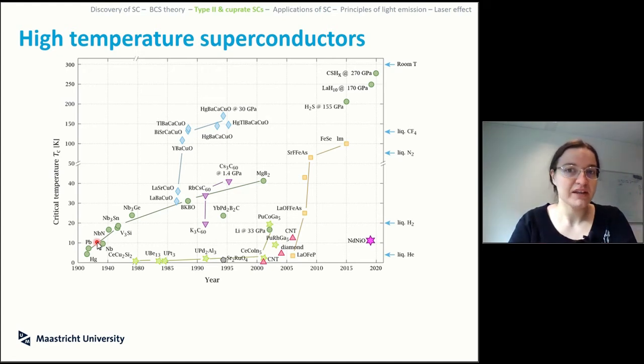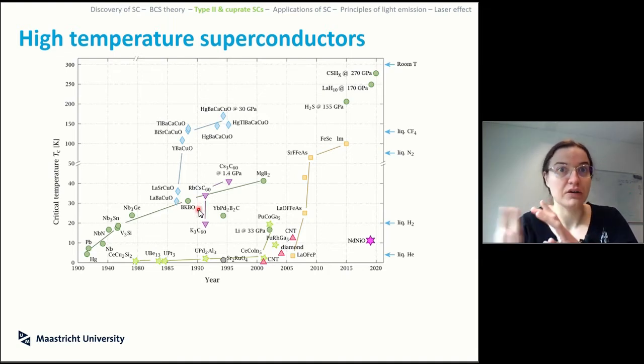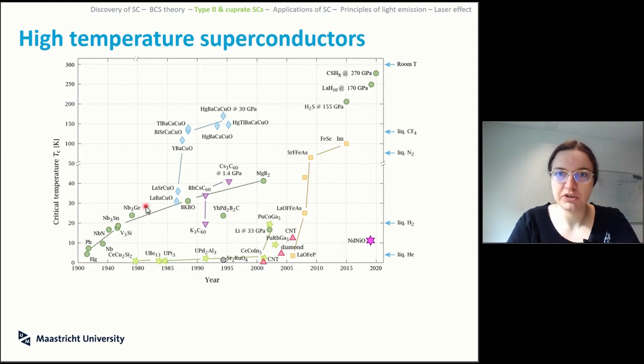And one of the biggest breakthroughs in this field was in 1986, in which they touched onto something that are the high temperature superconductors. And this was the first big leap, discovering this oxide phase, which, unlike the intermetallics, is a bit more like the complex oxides that we've seen in batteries. To begin with, in this composition, it was a lanthanum, strontium, copper oxide type of phase. We showed the superconductivity at 36 Kelvin, and this was already a Nobel Prize in itself.